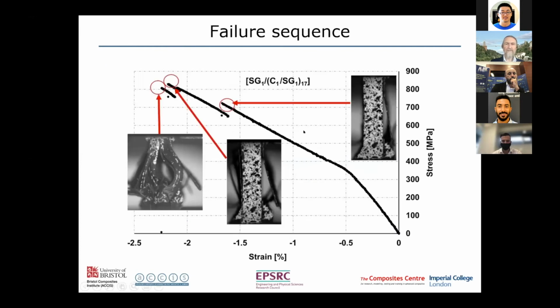We look at the specimen here, then we have the fragmentation occurring at this point here. Then we go quite a lot further, and at this point where there's a load drop, one of these surface plies has delaminated. You go a bit further, and the one on the other side delaminates, and then shortly after that, the whole specimen collapses, and we get complete failure. So that's what's happened when we have a single ply of carbon. And we get similar with the double ply, except it fails a little bit earlier.